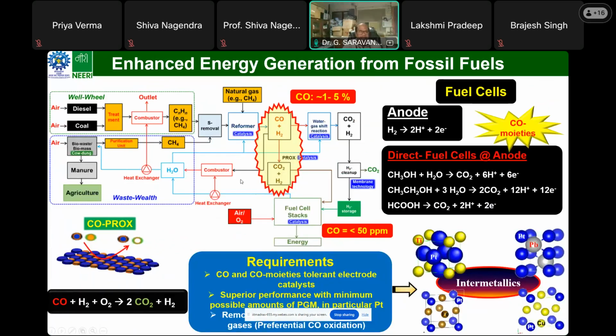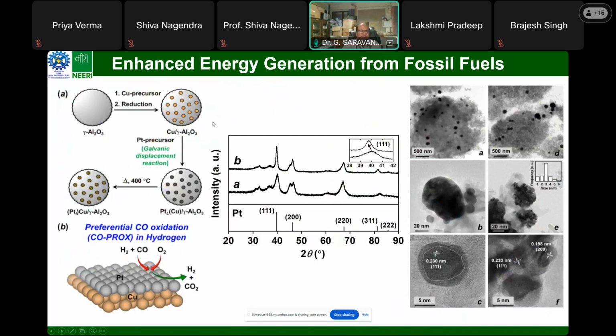Another point I was making is that we have to take care of preferential CO oxidation. When you generate hydrogen from fossils, which is what we currently use, the CO content is much higher. So we need to selectively remove CO from the hydrogen-rich stream. People are using platinum here, so we have developed a core-shell catalyst for this. Our idea is to minimize the platinum consumption for these applications.